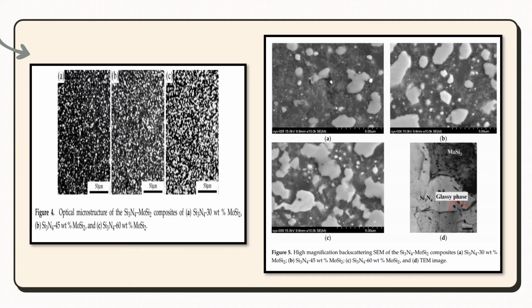Figures 4 and 5 show the optical microscopy, backscattering scanning electron microscope, and transmission electron microscopy images of silicon nitride with 30 weight percentage molybdenum disilicide, silicon nitride with 45 weight percentage of molybdenum disilicide, and silicon nitride with 60 weight percentage of molybdenum disilicide respectively. In the optical microscope and backscattering electron microscope, the white areas are the molybdenum disilicide phase and the dark areas are the silicon nitride phase. As seen in the figures, these two phases were evenly distributed, and the interfaces between the two components were clear and smooth. Little micro cracks could be observed.